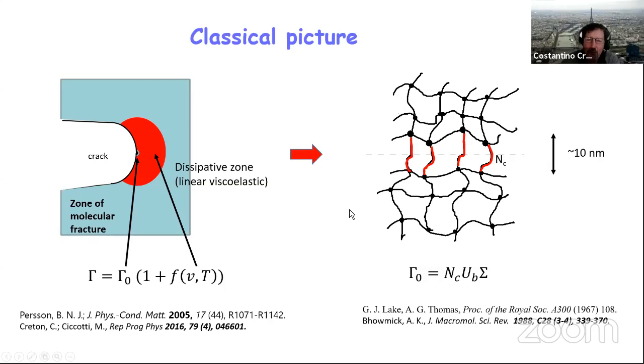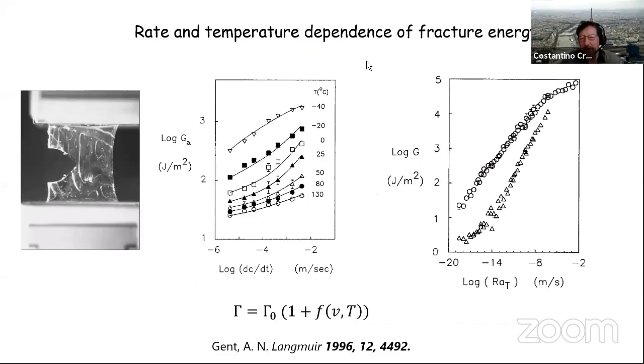The classic picture of viscoelastic fracture, in very general terms, is that in threshold conditions, you have indeed a Lake and Thomas type fracture energy, which doesn't have to be this. I mean, it can be more generally seen as a gamma zero. And then you have a rate and temperature dependent dissipation, which can in principle be obtained from linear viscoelastic material. And there will be a small zone here where linear viscoelasticity does not really hold, or indeed you could have a zone of molecular fracture. I've been arguing for a while that this zone of molecular fracture was not that small, and that it really should be incorporated in the model. If you look at experiments, though, it's not that obvious.